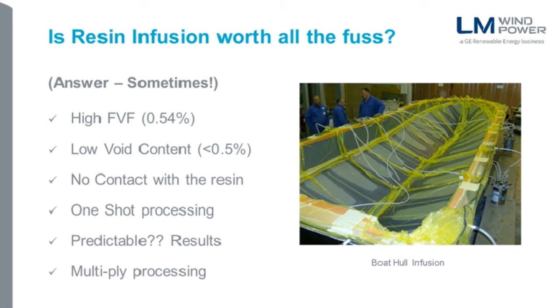If you haven't got that with resin infusion, you really shouldn't be starting. And generally, tools that look like they've got vacuum integrity, but you haven't tested them, aren't. You do a drop test on them, you do a vacuum leak test, and you find that they're cracked or they're leaking, and they won't hold a vacuum. And the challenge with moving ahead with a tool like that is inevitably you don't get the outcome or the result that you wanted. And then everybody's disappointed and blames resin infusion rather than looking at the root cause, which is a leaking mold or a design that isn't robust. So that's part of the fuss.